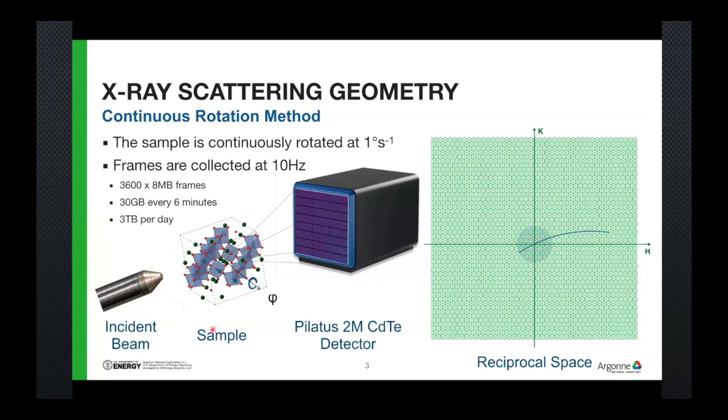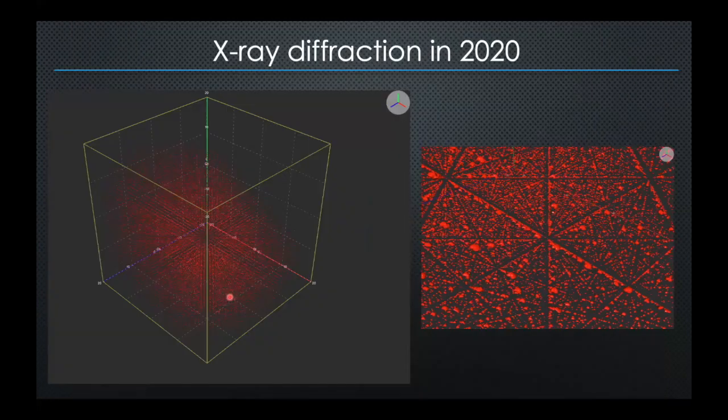But the point is, as you rotate crystals these days and use a high energy incident beam, look at the number of reciprocal Brillouin zones that it's covering. This one arc is the Brillouin zones that get covered by one angle position. And as you rotate this crystal in 0.1 degree increments, you're collecting terabytes of data. And this is what the data looks like.